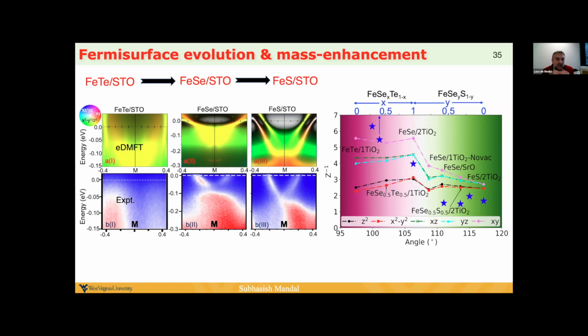Typically when you have several sheets in the Fermi surface, you have two large pockets. I think it was understood that if you reintegrate some kind of Hartree-Fock treatment of the non-local exchange, you get the size of the Fermi pockets back to what experiment gives you. So in estimating how you make the whole pocket disappear, maybe hybrid functionals or Hartree-Fock corrections have some role to play.